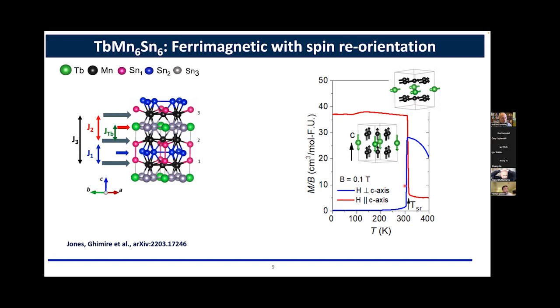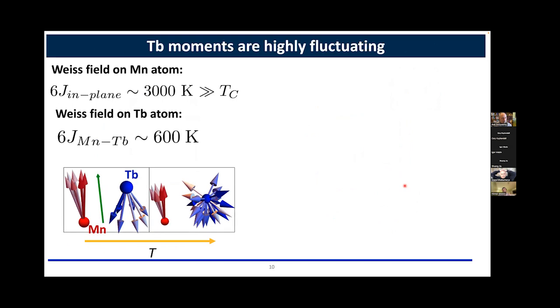And we now think that, in a very simple mean field model, we can understand what is causing this spin reorientation. Again, very quickly, I will explain this: if we look into the Weiss field on the manganese atoms and terbium atoms, the Weiss field on the manganese atom is pretty large as compared to the Weiss field on the terbium atom. Because of this, the terbium atom fluctuates more. This is shown here in the cartoon picture as compared to the manganese atoms. At lower temperature, the manganese atoms are not fluctuating as much as the terbium atoms. But as you increase the temperature, the terbium atom fluctuates much more than the manganese atoms.